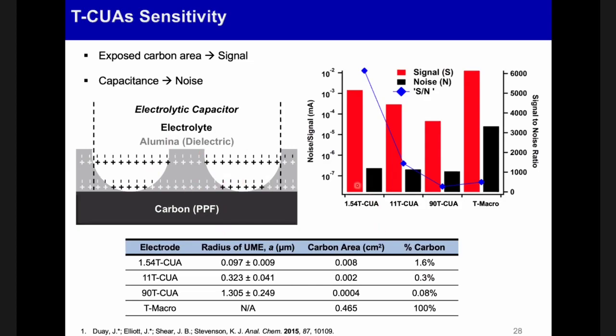If we take a look at the signal and the noise separately at each of these electrodes, in particular, this is the no array electrode, you can see the noise is significantly higher. If you look at the difference in dielectric constants between water and alumina, that explains why we see this difference in noise. And our signal goes back to the exposed carbon area, and it's highest when we use the smallest diameter. So we get the highest carbon area, and we're able to achieve the best signal to noise ratio with this electrode geometry.